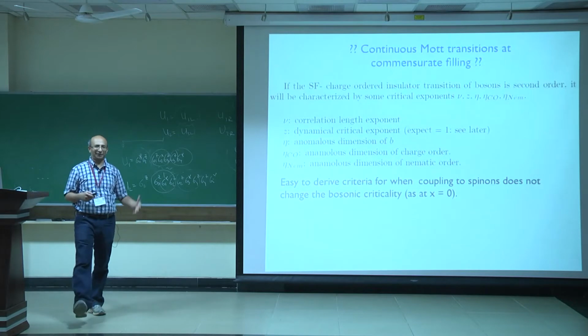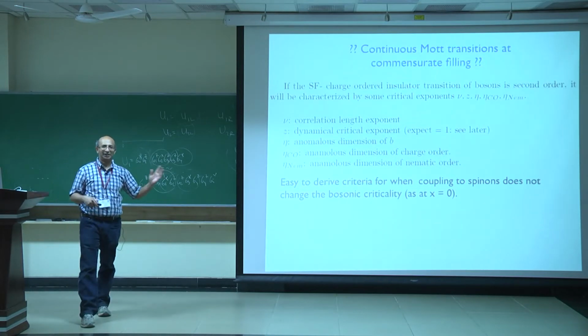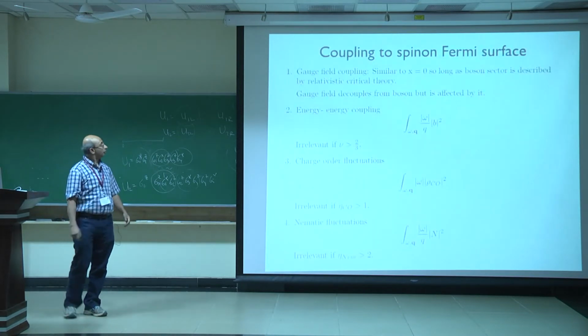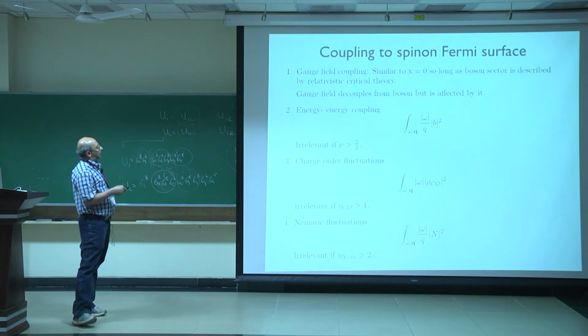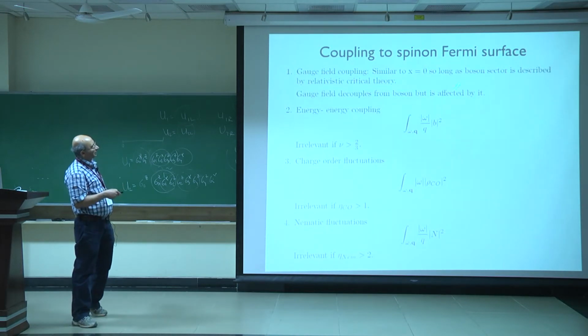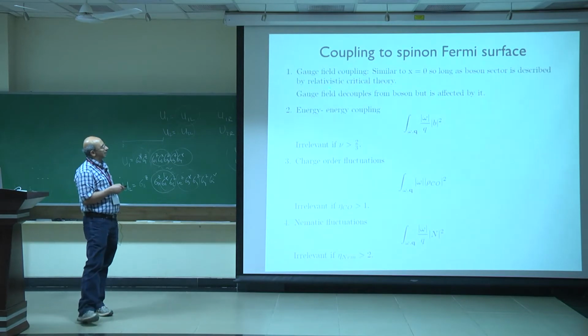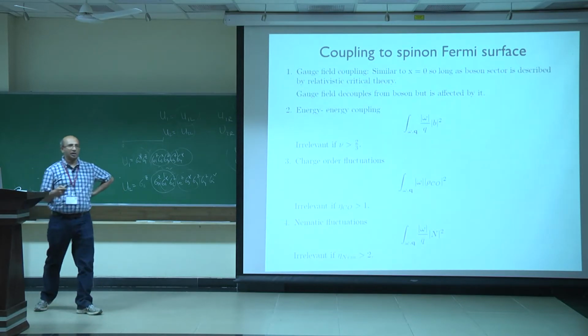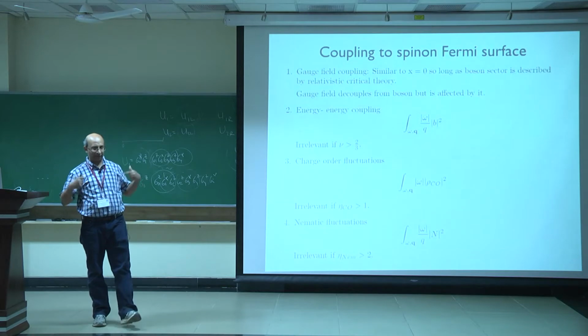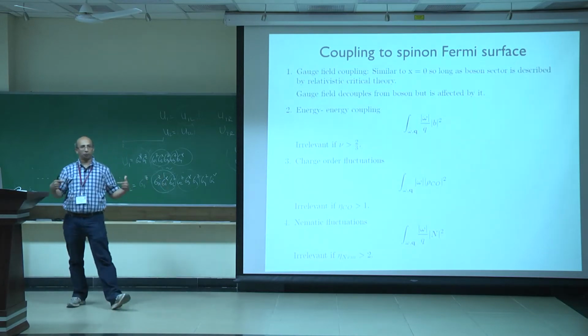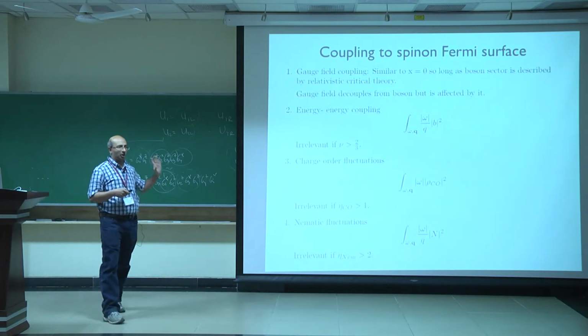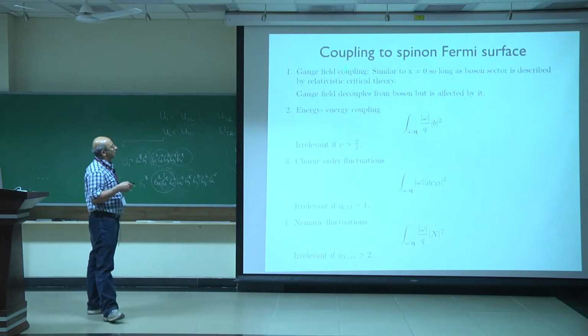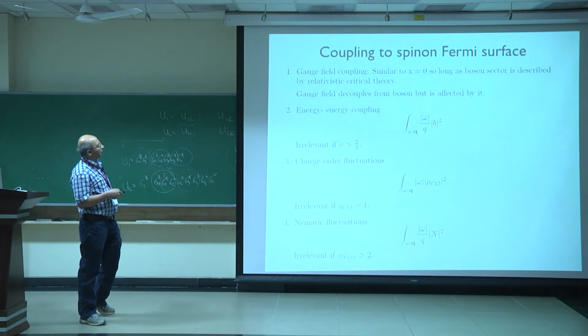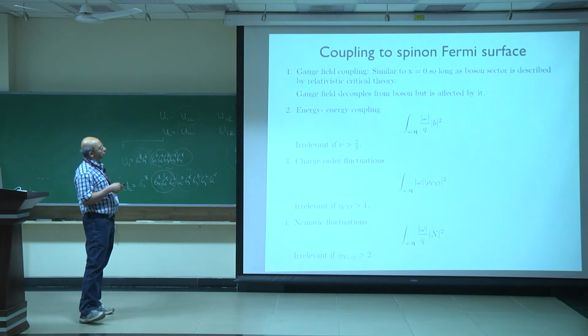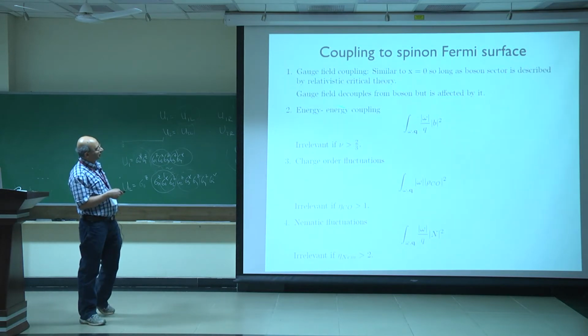Okay? Because if that happens, then life is really simple and we can work everything out. So the gauge field coupling is similar to what happens at x equals 0. So long as the boson sector is described by a relativistic critical theory, because the Landau damping of the gauge field will still continue from the spinon Fermi surface. And so long as the charge sector is described by a relativistic CFT, the arguments that I gave before will continue to hold, and particularly the gauge field will decouple from the boson, but will be affected by it.